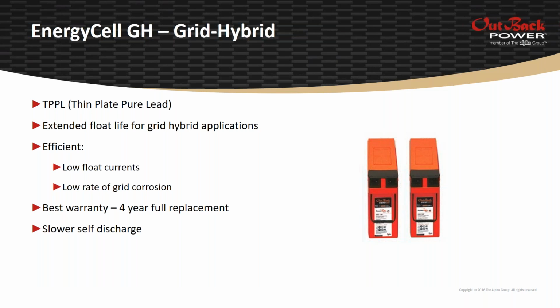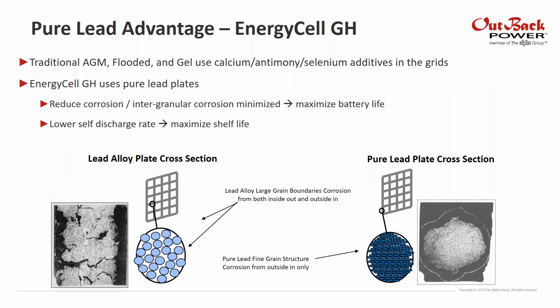These batteries are also really efficient batteries. So the efficiency is really tied to the rate of corrosion of the plates. The grid corrosion in typical AGM batteries is due to the additives and the impurities in the lead. Actually, we'll just go ahead and skip to the next slide. So you can see here on the bottom left, that's a lead alloy plate cross section, and those grains are big. They're, again, not uniform. They just rub together kind of the wrong way, and they increase the rate of corrosion. Whereas on the right-hand side, you see a pure lead plate that has very, very small grain boundaries, and those small grain boundaries make it really hard for that metal to corrode. So it significantly slows the corrosion rate.